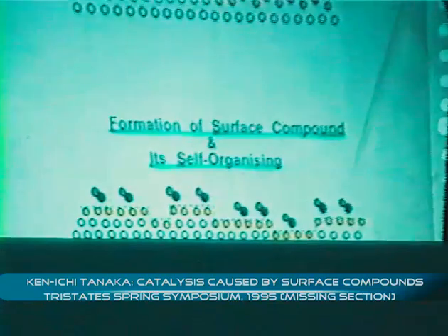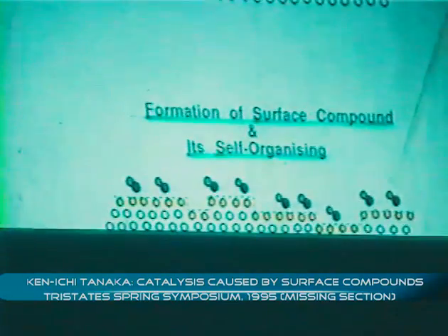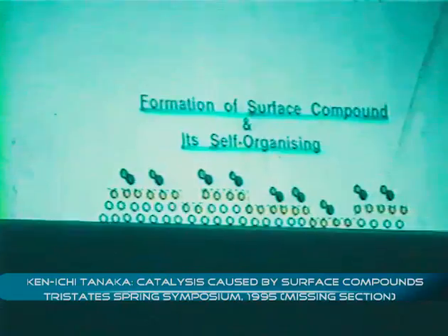That is, incoming molecules react with metal atoms which derive from the surface, in some cases from terraces, in some cases from steps. This phenomenon is a very important advantage of heterogeneous catalysis, because even at room temperature we can self-synthesize functional compounds on the surface. Such surface compounds sometimes promote the reaction, sometimes they are the reaction intermediate itself, and in some cases such formed compounds stop the catalytic process.